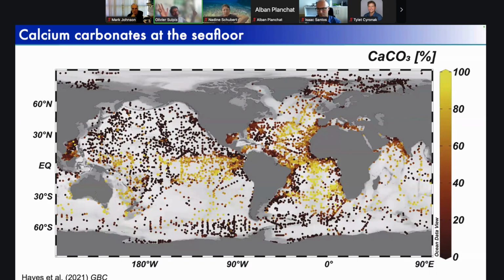Here, it's mostly the influence of the environment because the bottom waters that are in contact with this seafloor are much more acidic at the north of the Pacific than in the Atlantic, because those waters in the Pacific are very old, several centuries, even some millennia old, and they have had a lot of time to accumulate a lot of metabolic CO2. So they are more acidic, and therefore calcium carbonates have a harder time being preserved here.